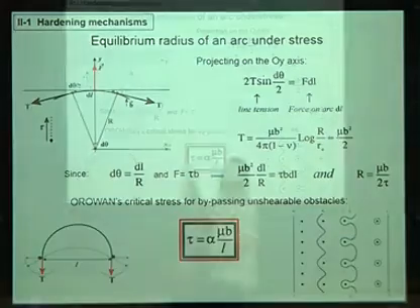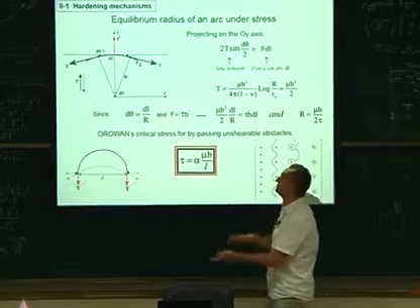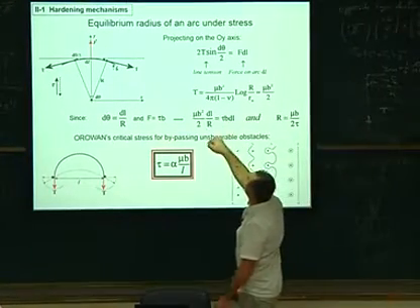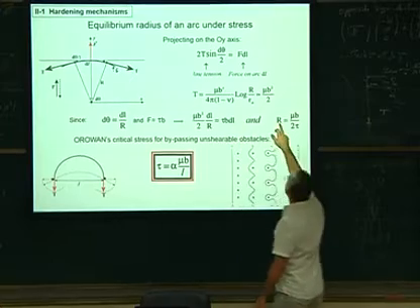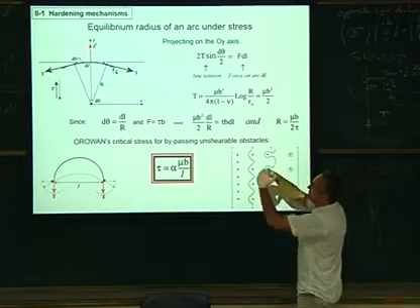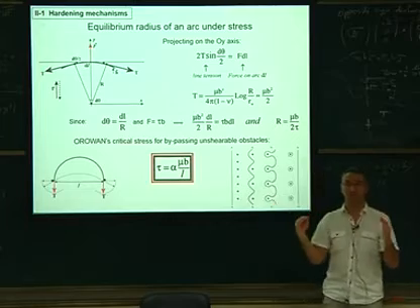And if you say that F is equal to what you apply, tau b, you see the force is the shear times the Burgers magnitude, and you put that in the equations, and finally you found that the curvature is mu b over twice your shear stress. So this gives you the curvature of a dislocation.